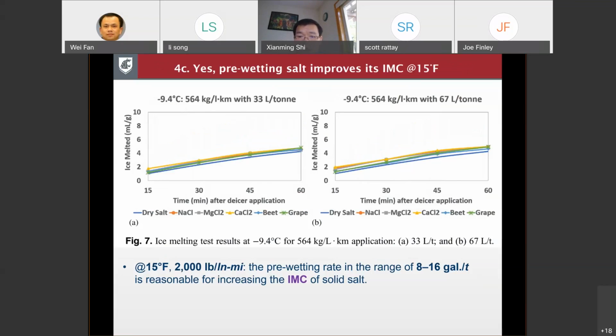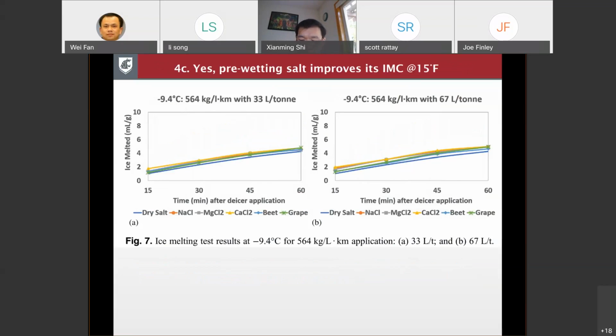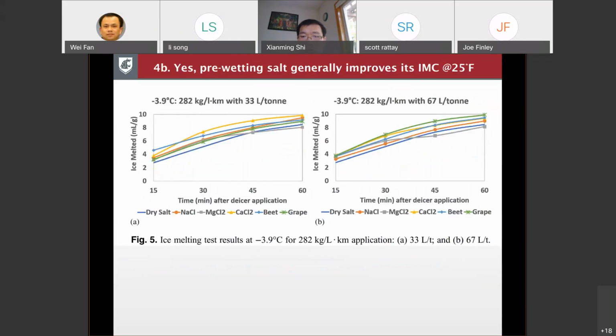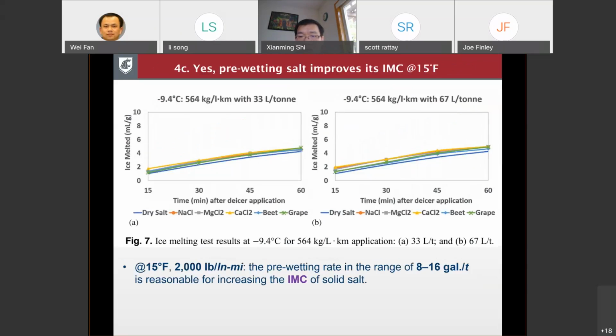And the trends are very similar, but in the colder temperature, the differences between the pre-wet liquids, however, sort of diminished. If we go back, here, this one, we're seeing much more different behavior. When it gets colder, the type of products actually don't make as much difference. But they're all better than the blue line, which is the control with the dry salt.